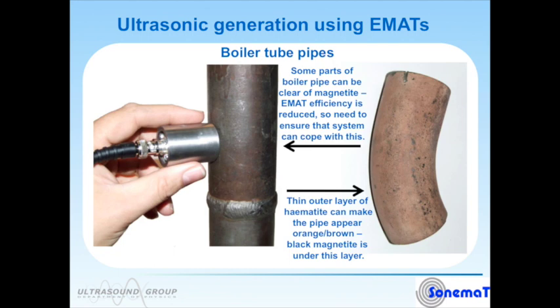Generally, pipes like those on the right of this image will have much thicker magnetite layers under this very thin top surface of hematite. The pipe on the left as shown here may actually have regions where there is very little oxide surface coating.